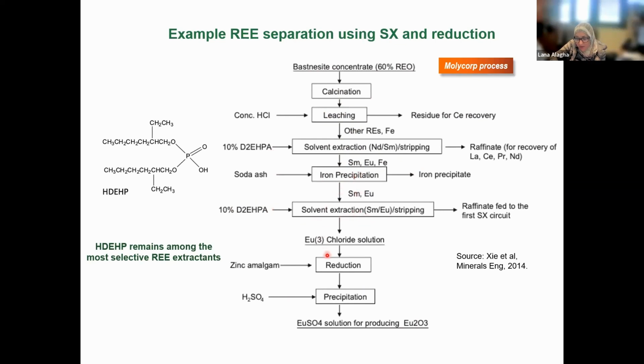And then again, you can see similar separation processes, and you end up with europium, which is in the oxidation state 3 here in a chloride solution, and then you add zinc to reduce it to europium 2. After that, you add sulfuric acid to convert europium 2 to europium sulfate, and then calcination can again convert the sulfate to oxide.